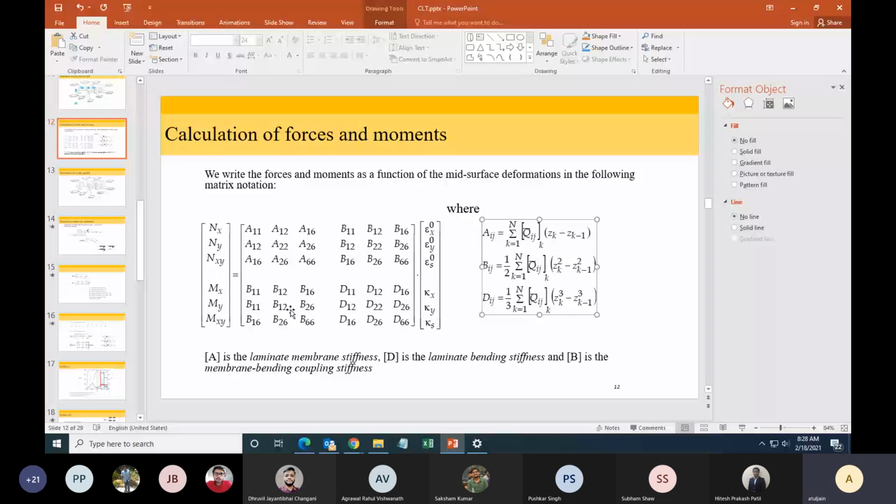It also, from the point of view of manufacturing, if you have a non-symmetric laminate where the B matrix is non-zero, and you put it in the autoclave for curing, what is going to happen? There are going to be in-plane residual stresses due to the temperature, but since the B matrix is not zero, that is also going to lead to curvature. So you will never get a completely flat plate. There are always going to be some warpage or some defects.